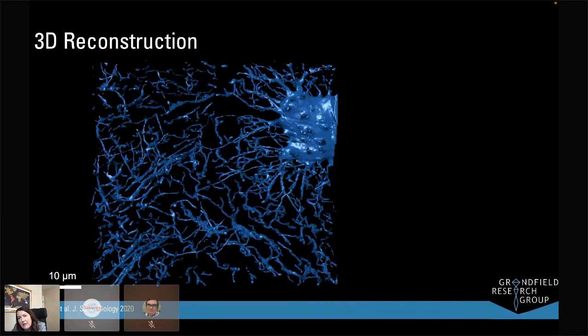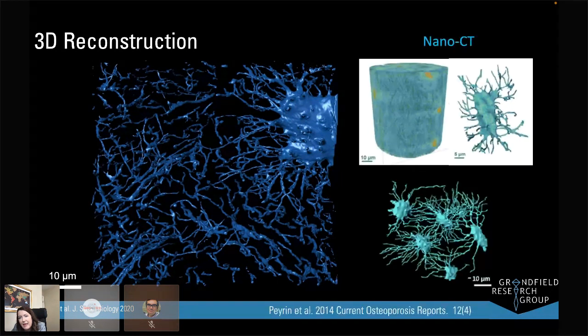This is exciting because it starts to approach the length scale or volume of what you could achieve if you went to a synchrotron. This is an example on the right of nano CT or synchrotron-based CT experiments, which are fantastic and give us high resolution and large volumes. But of course, one has to travel to a synchrotron to obtain this data. The advantage with the plasma FIB is these are experiments you can do in your lab without traveling to a synchrotron.